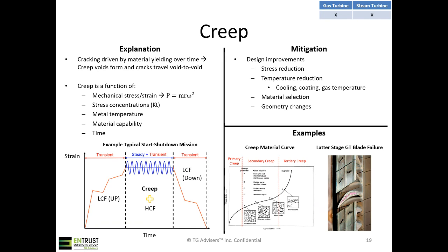Creep is the next item we'll talk about. It's basically cracking driven by the material slowly yielding over time. The material will stretch and form voids, and then cracks typically will begin to connect those voids as the voids get larger and larger. Creep is a function of mechanical stress and strain, stress concentrations, metal temperature, material capability, and most importantly, time. Creep is something that occurs over time.